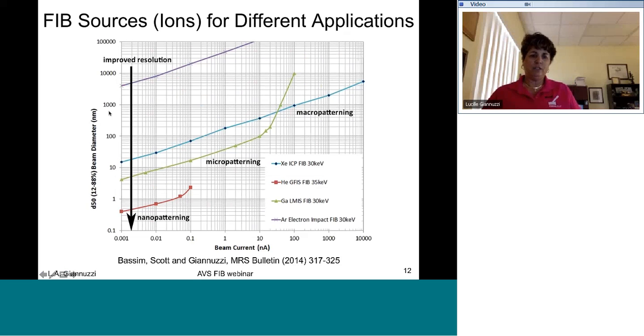So at the very high end, if we take a look at this log-log scale, you see that we can achieve pretty high currents, but very large beam diameters, and this is sort of an argon electron impact source type of a FIB, if you will. So these are the type of instruments or sources that you might see in an ion polisher, which is typically used now to cross-section huge amounts of material very quickly. Some of these don't have a focused beam per se. They're just a very large opening, and some do scan the beam, but mostly you're just talking about opening up the beam, or allowing the beam to come through a very large aperture that hits everything in its line of sight.